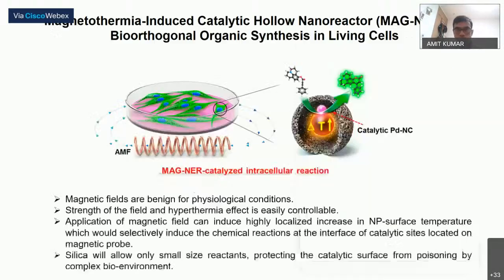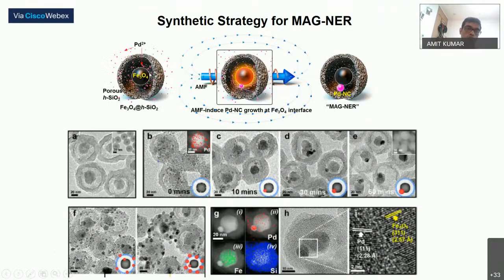Okay, so the third, which is like final part of my presentation, is we actually thought instead of light, can we apply magnetic field to induce intracellular chemical reactions? Because magnetic field is extensively used, and it is very benign for biological conditions. And the strength of the field and the magnetic hyperthermia is easily controllable. So we thought to modify the catalytic sites interfacial to the magnetic nanocrystal. And when you apply alternating magnetic field to such a system, it can generate localized magnetic heating, and which can promote chemical reaction.